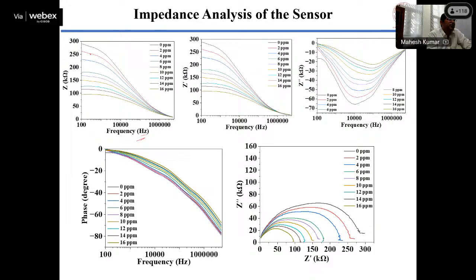So here, from 0 to 16 ppm, we have used different ppm, and the impedance depends on the concentration of the gas. Again, we have measured the real part, and this is the imaginary part. We have also measured the phase. So this is varying with frequency.